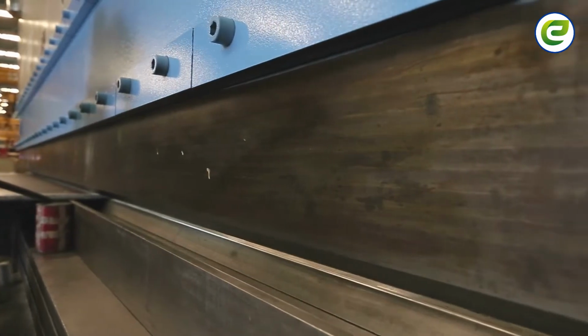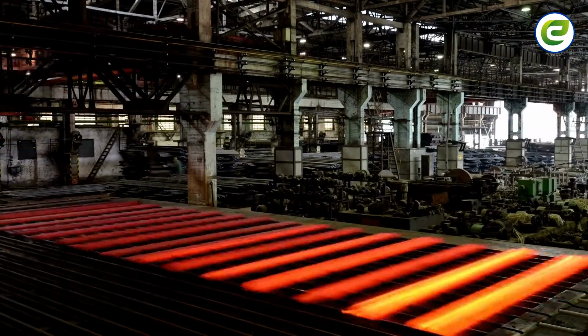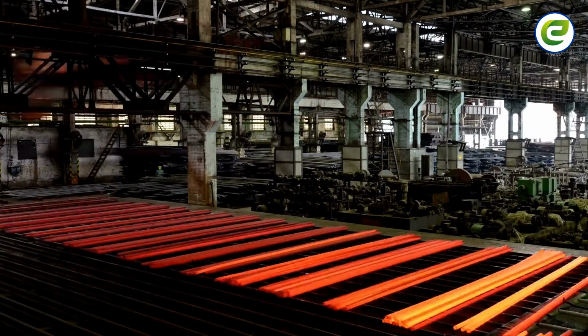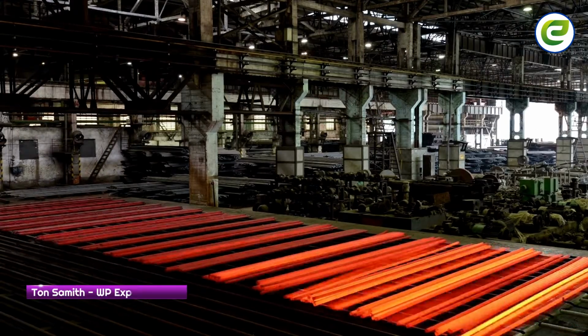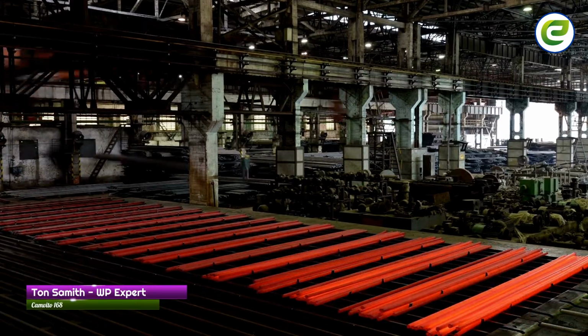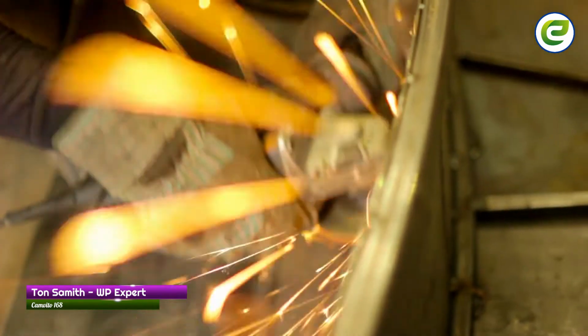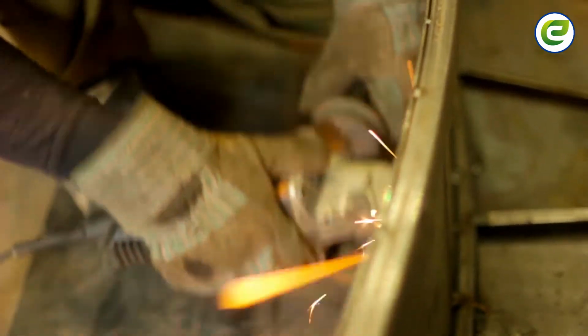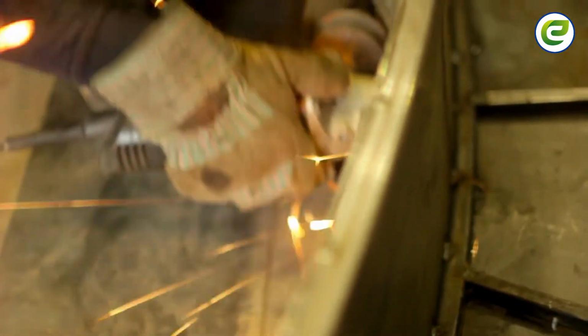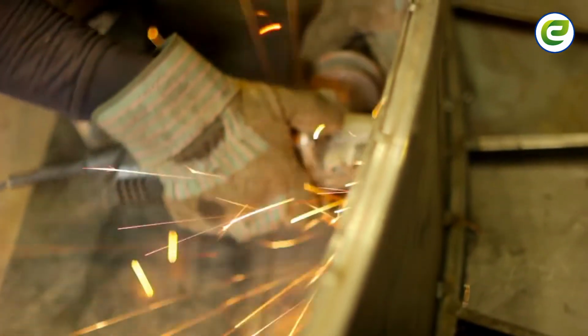Microalloyed steels. An important development immediately after World War II was the improvement of steel compositions for plates and sections that could readily be welded. The driving force for this work was the failure of plates on the Liberty ships mass-produced during the war by welding, a faster fabricating process than riveting.